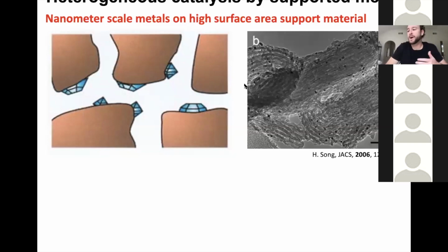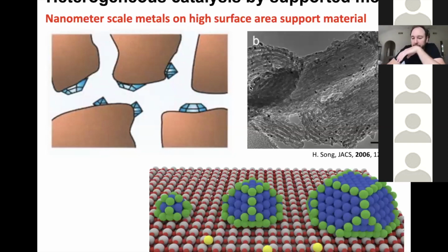So if we think about what makes up supported metal catalysts, you can think about it at a little bit finer scale. So here my red and my white balls are an oxide support. And these various different domains here are active metal species. And so I drew these a few different ways. In this case, at the smallest scale, this is something like a 1 nanometer particle, metal particle. This is maybe up to a 2 or 3 nanometer diameter metal particle. The blue balls here are surface atoms that are well coordinated to their neighbors. So they're making something like 8 or 9 bonds to their neighbors. These green ones are edges, and these are making maybe 5 or 6 or 7 bonds to their neighbors. And you can imagine that their varying coordination causes very different reactivities.